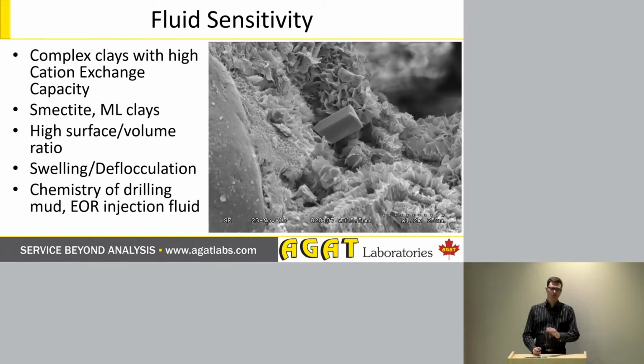If we change the fluid chemistry surrounding these clays, we can induce physical swelling up to 10 times their volume. This means that we need to be very, very careful when we're considering the chemistry of drilling mud, enhanced oil recovery injection fluid, and so forth.